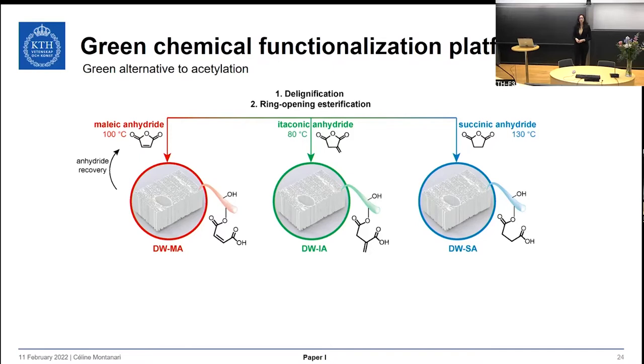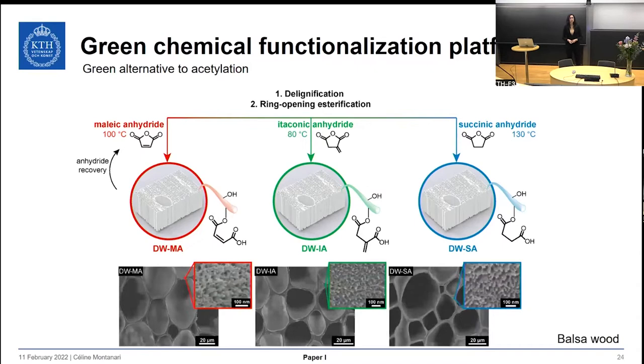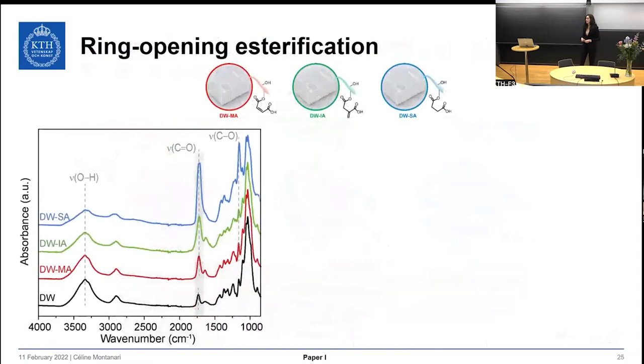The functionalization was performed under solvent-free reaction conditions above the melting point of each anhydride. The reaction proceeds via ring-opening esterification of the anhydride and results in functionalized wood substrate with introduced functional groups, including terminal carboxylic acid groups as well as monosubstituted alkene and disubstituted alkene in the case of itaconic and maleic anhydride respectively. After the functionalization, the wood microstructure is preserved as well as the nanostructure at a scale of 100 nanometers.